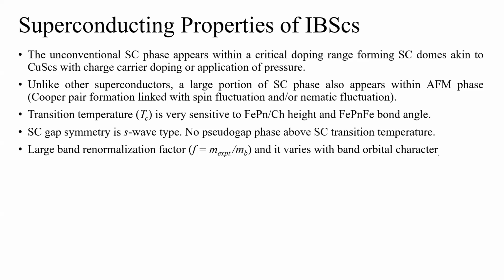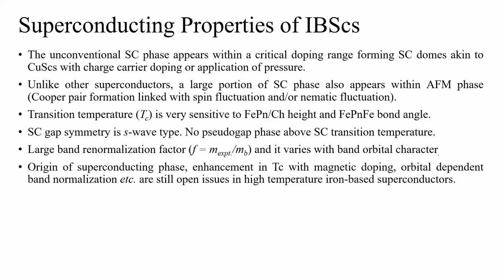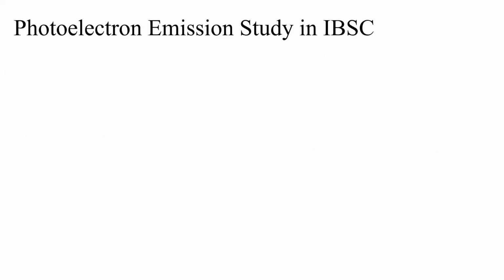renormalization factor, and this renormalization factor also varies with the band orbital character. So a few bands have dxy character, and the bands which have dxy character have a larger renormalization factor in comparison to the other bands. The superconducting phase and the enhancement of Tc with magnetic doping such as cobalt, nickel, and the orbital band renormalization are still an open issue in these iron-based superconducting compounds.